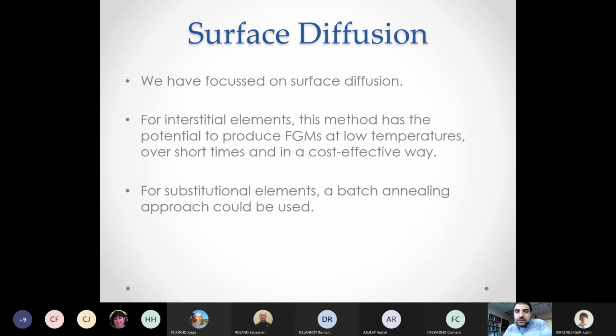So we've used mainly the method of surface diffusion in our research, and we tried to look at ways of introducing a composition gradient at the surface. We tried adding or removing carbon at the surface, and the advantage there is carbon has a strong impact on the properties of the steel, and at the same time, the diffusion of carbon is very fast. So this makes this approach a simple, practical, fast approach to make a graded material.